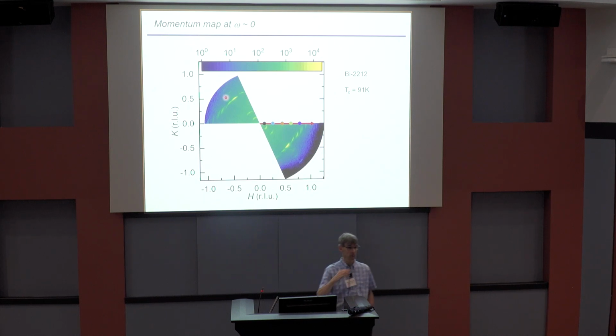You see them also if you take an STM spectrum and Fourier transform it, you see peaks in the same location. So all this works well. By the way, you can think of this as energy resolved LEED. LEED is low energy electron diffraction. This is basically a LEED pattern looking at only the elastically scattered electrons. And what I'm going to show you are data stepping along this direction in momentum space where we can avoid a lot of these supermodulation reflections.